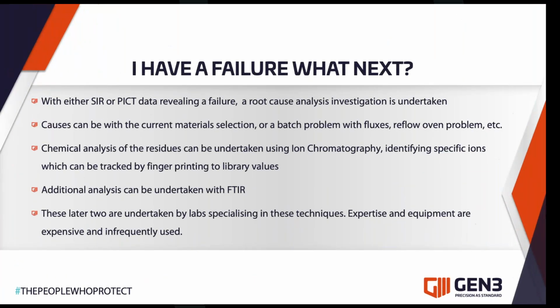What next? If SIR or PICT data reveals a failure, a root cause analysis investigation is undertaken. These causes can be with current material selection, a batch problem with fluxes, a reflow oven problem, and multiple potential causes. This is where chemical analysis of the residues can be undertaken using things like ion chromatography, which helps identify the specific ions, which can be tracked by fingerprinting to library values. Other techniques include FTIR, Fourier transform infrared. These latter two can be undertaken by labs specializing in these techniques because they are expensive, difficult to do, and complicated to work out, and so really should be used only for root cause analysis. Expertise and equipment are expensive and infrequently used.